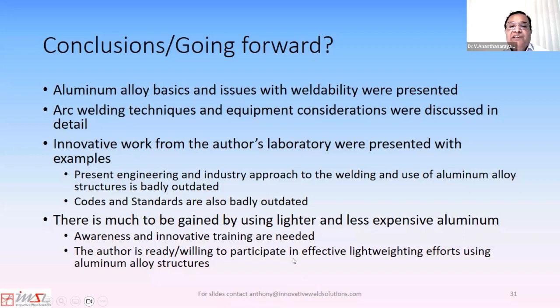Which process, GTAW or GMAW, is advisable to weld thin sheet lap joints, for example on the roof of a train car or a sidewall? If your volumes are large, I would recommend using GMAW with very good welding current pulses, as I showed in some of my earlier slides. Particularly because I believe these are not subject to too much loading. They're mainly meant for providing a good cover. I'm not sure they are subjected to a lot of mechanical loading. So a good GMAW with good productivity may be a good answer for you.